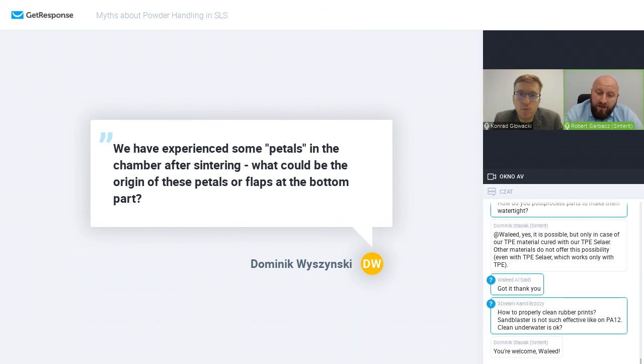Or if you mean when you're sandblasting, when you're taking the print cake out and you see some small flat parts of the powder that are left after printing, not the part quality, but some Sinterit powder which is not the part, on the very, very bottom, it's totally okay. It's part of creating a safe environment for starting printing.